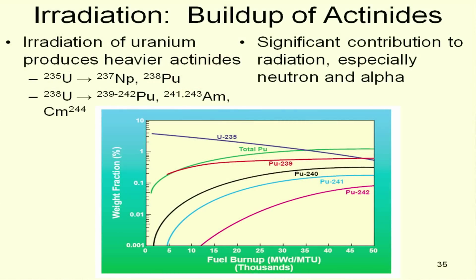Buildup of actinides. I referred to some of this before, but this is a generic buildup curve, whereas your U-235 is going down, the total plutonium and the other isotopes are coming up or staying pretty level. When you reach the end of life, depending on the burnup, roughly 60% of your fissions are coming from plutonium as opposed to the U-235. The U-235 is about shot.